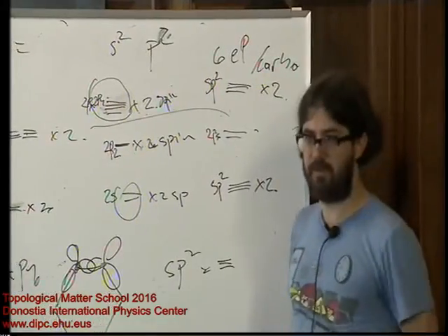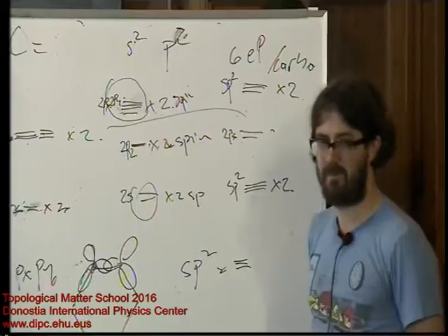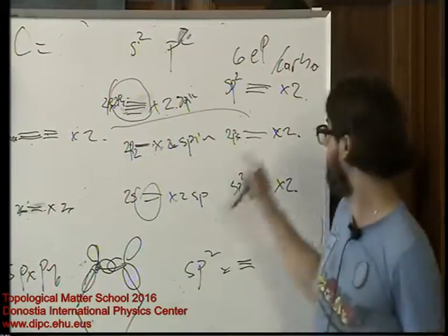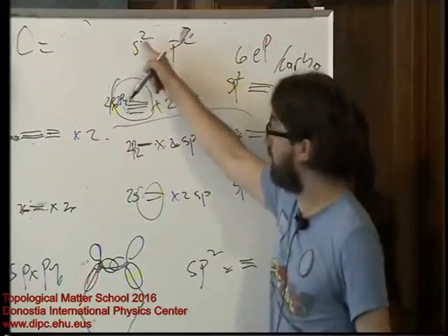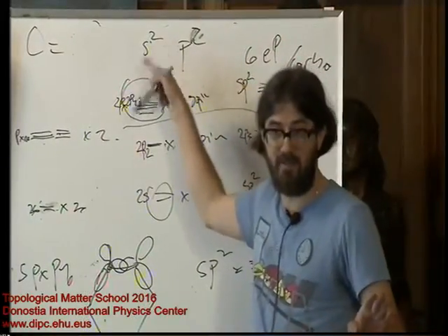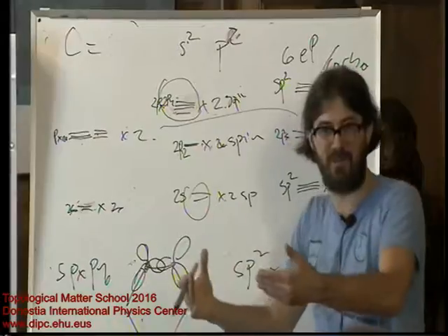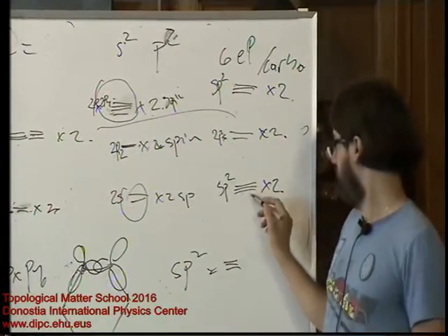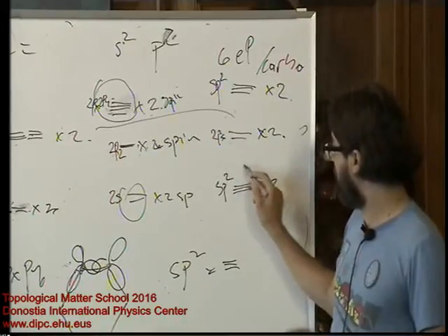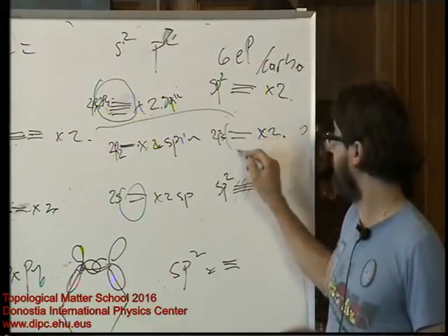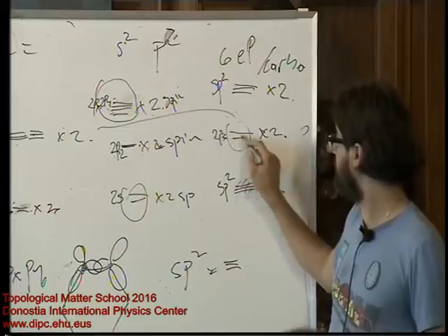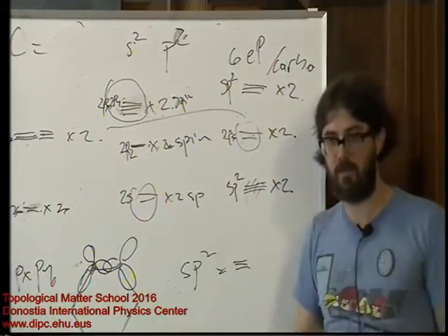Now, where does my Fermi level sit? I need 6 electrons. By the way, these are electrons with spin, in carbon. When you go to the periodic table, you get all the electrons. I have 6 occupying all these, but I have 4 bands, 2 times 2 spin. I occupy them with 2 electrons, so the Fermi level sits in the middle. That's why graphene is a semi-metal.